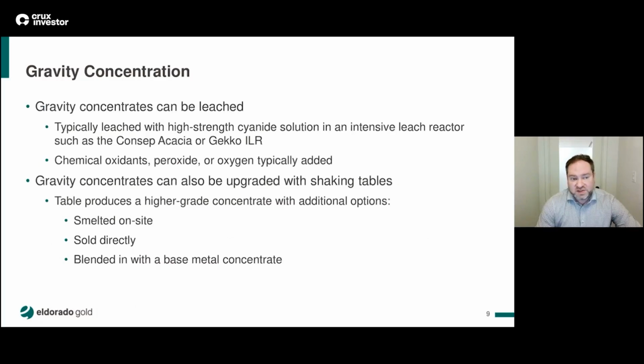Following recovery of a gravity concentrate, they can typically be leached in intensive leaching. Two options are the Consep Acacia reactor or the Gekko ILR. These reactions are required to be carried out with chemical oxidants, either peroxide or oxygen, typically at high cyanide strength, because of the very high concentrations of gold that are leached in these reactors. The concentrates from gravity can also be upgraded with shaking tables, and that high-grade concentrate can either be smelted on site, sold directly, or in some cases blended in with a base metal concentrate that's being produced by flotation.